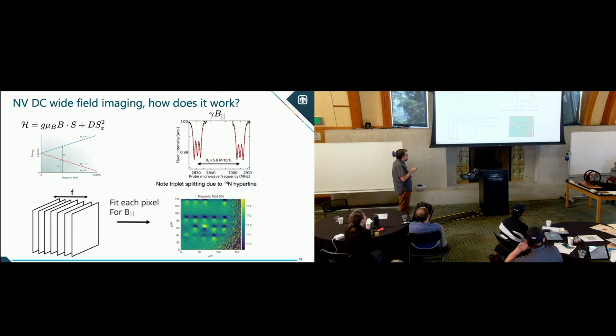And what we do is we take this spectrum, we take pictures as a function of frequency drive. So each picture actually will have a spectrum in it. And then you can take all these pictures and all these spectra, fit them for the magnetic field, and you can get a magnetic map. Now in this case, this sample was micron-scale bar magnets that we intentionally fabricated to qualify our quantum sensor. So you can actually see the dipolar shape of a magnetic field from these nanomagnets.